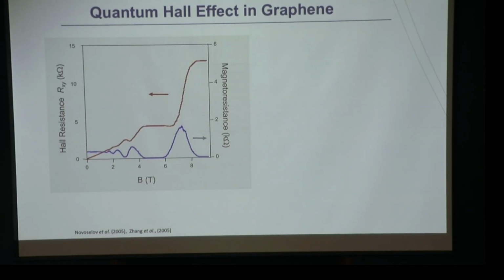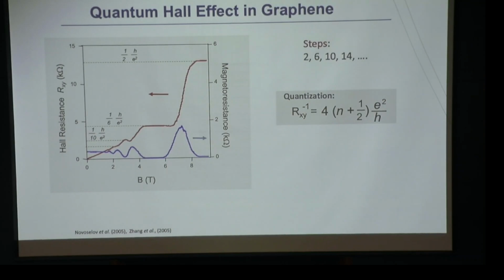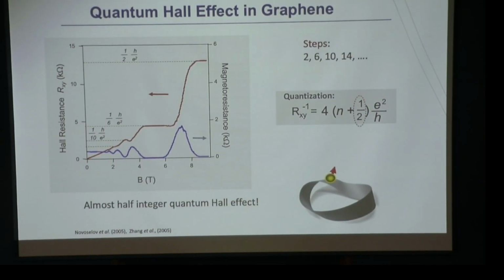The next year, that competition between Manchester and Columbia showed that with high enough quality of this two-dimensional system with the Dirac dispersion relation, you get this big quantum Hall effect where the sequence is rather intriguing. The sequence goes like 2, 6, 10, and 14, and you can quickly say this is nothing but a generalization of 4 times a half integer. In fact, the very existence of the half integer is precisely related to the Berry phase, meaning that turning around once on the orbit is equivalent to a half count. That is the meaning of the half integer, precisely showing the importance of the Berry phase associated with the system.